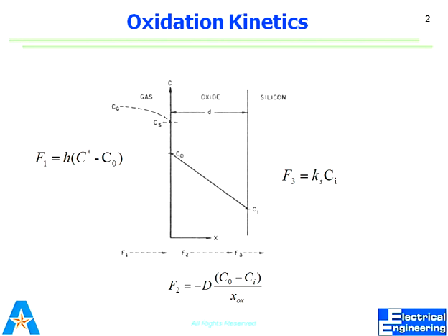First part is that the oxygen molecules need to come from the source, wherever the oxygen source is, towards the wafer surface. That is up to this point. And the second part is that the oxidant needs to diffuse through that oxide layer to reach the silicon. And after that, it needs to have a chemical reaction with the silicon, that is F3. So now you will get that idea that actually F1, I say...